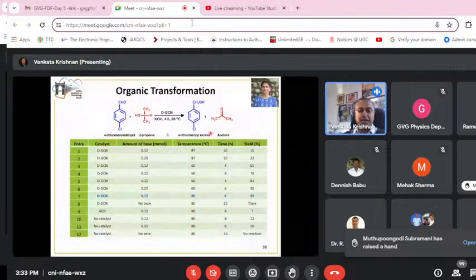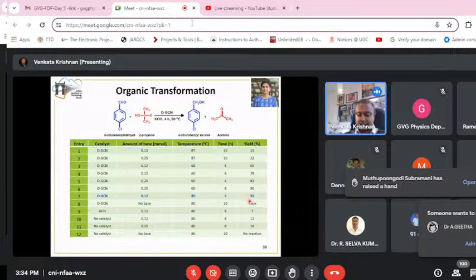Then we took this reaction wherein 4-chlorobenzaldehyde gets converted to 4-chlorobenzyl alcohol in the presence of 2-propanol. The 2-propanol is used both as a solvent and as the hydrogenation agent for the transfer hydrogenation, in the presence of our catalyst. What happens is these two hydrogen atoms get connected to form the alcohol group, 4-chlorobenzyl alcohol, and as a result, the 2-propanol gets converted to acetone. This is the transfer hydrogenation reaction, and for one of the conditions, we got the best yield, which is about 92%.